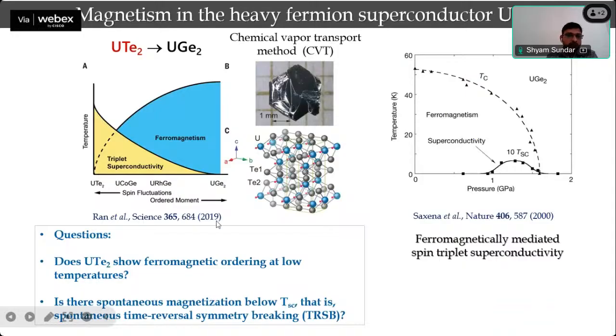When this was discovered in 2019, it was very important to find out whether it shows magnetic ordering at low temperature, below the superconducting transition, and another thing, whether it shows any time reversal symmetry breaking, because this is a ferromagnetic superconductor. They cannot show spin singlet pairing. That means the Cooper pairing cannot happen with spin up and spin down. So either both spins have to be spin up or spin down, which is called spin triplet pairing, and which is supposed to show time reversal symmetry breaking in these materials. So we were looking for two different things: whether it shows ferromagnetic ordering at low temperature, or whether it shows time reversal symmetry breaking or not.